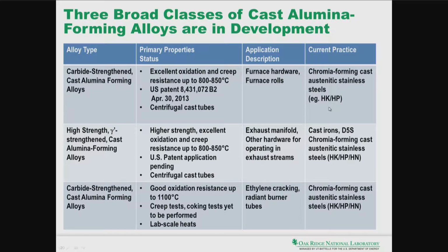And the second class of alloys that we have are relatively higher in strength than the HK and the HP type of alloys. They have much higher strength, and they have a much sharper drop-off in strength above these temperatures. So there's a hard limit as to temperature, maybe about 900 C. It's probably the maximum that you would be able to use these alloys. We have a US patent application pending on these. Again, they could be used in centrifugal cast tubes and or shaped components.